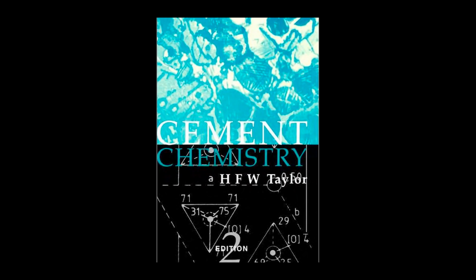And finally, the ultimate high-performance additive, silica fume. Silica fume is a highly refined industrial byproduct. It consists of incredibly small, non-crystalline glass spheres, often only 100 nanometers in diameter. Its ultra-fineness provides two massive benefits. First, it has extremely strong pozzolanic activity, so it rapidly consumes CH to form high-quality CSH.